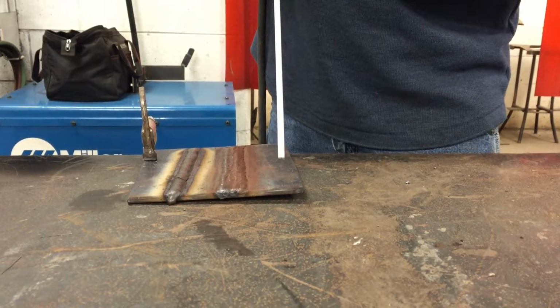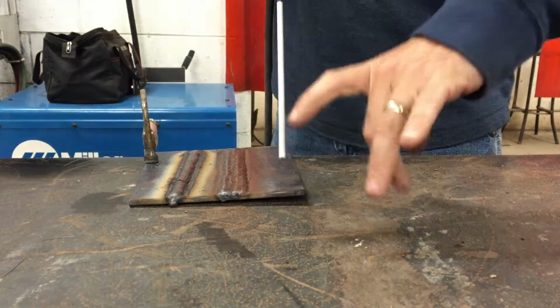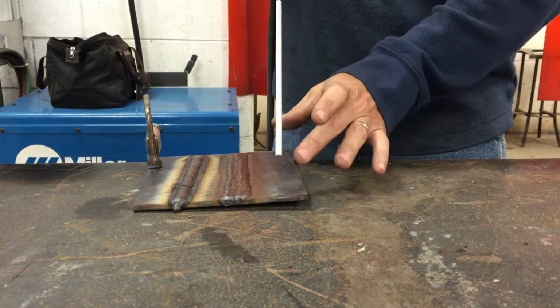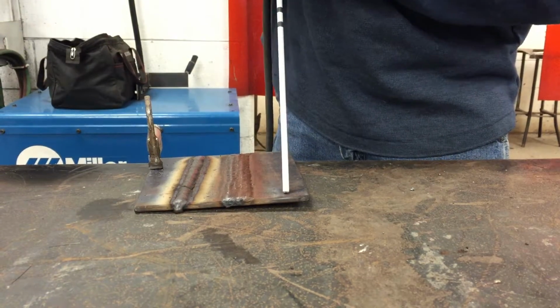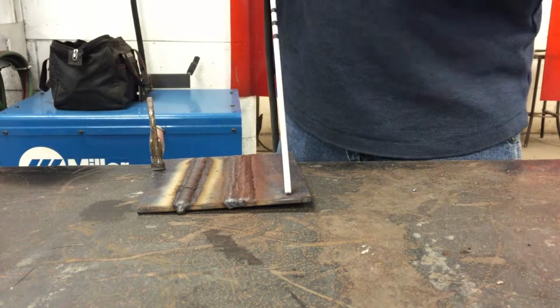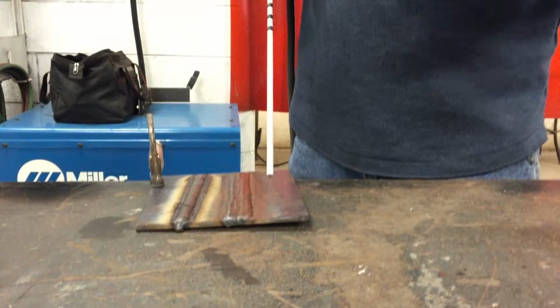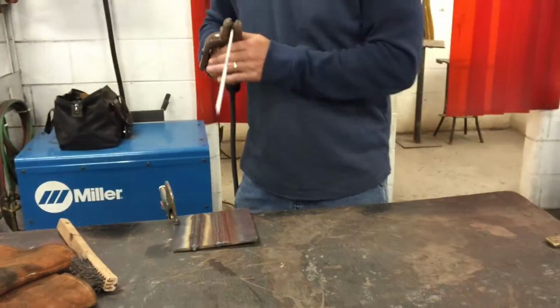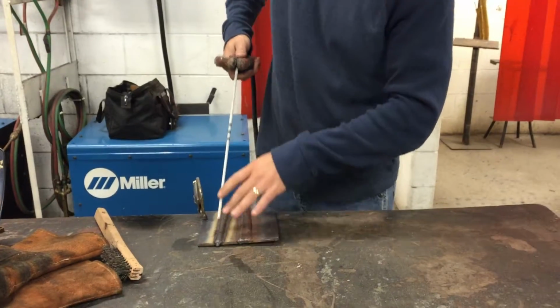You don't want to get too long. If you do, it's just going to splatter everywhere. You'll get a lot of contamination. If you drive the welding rod into the metal, there's a possibility of it sticking, then you have to stop, clean, and start back over. So, I've made my weld.